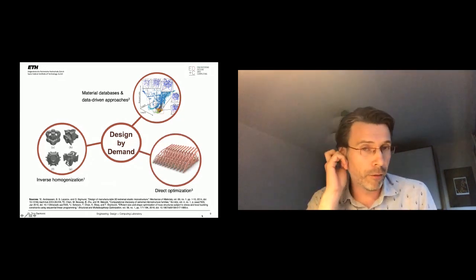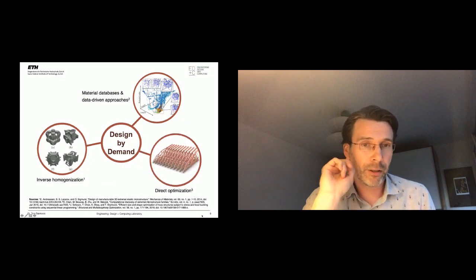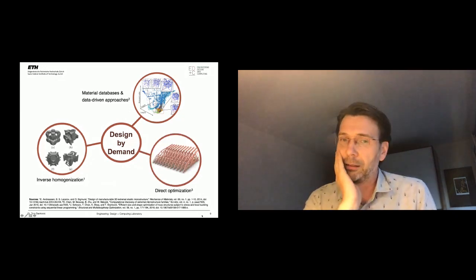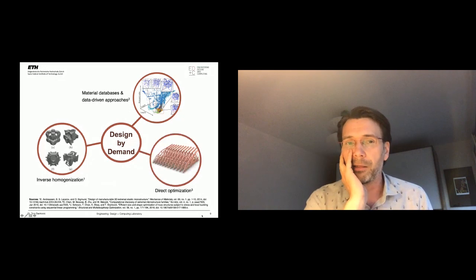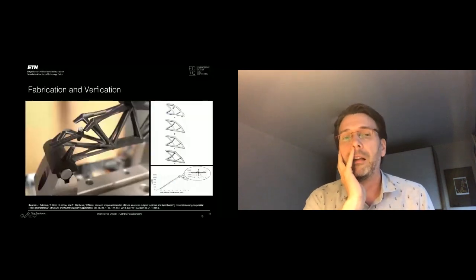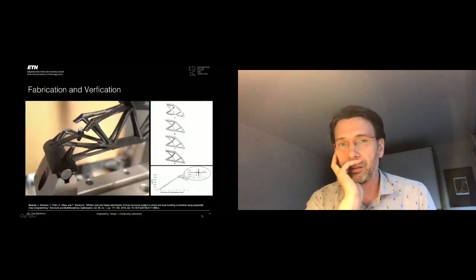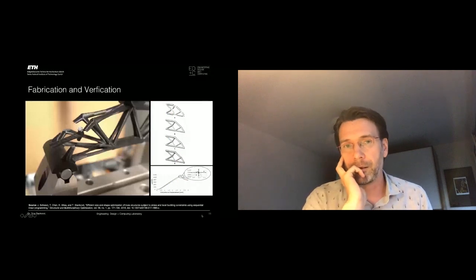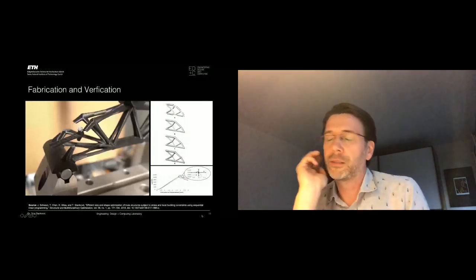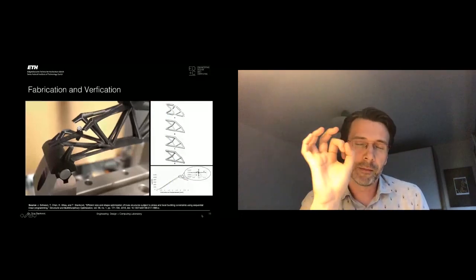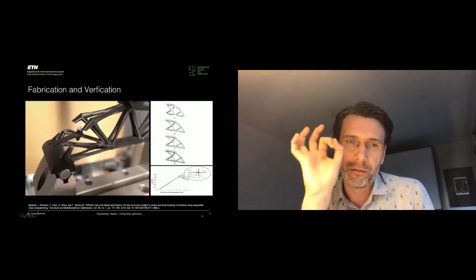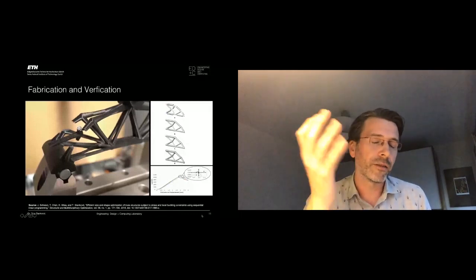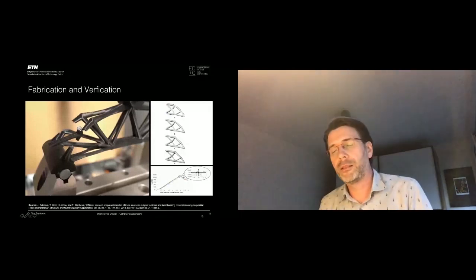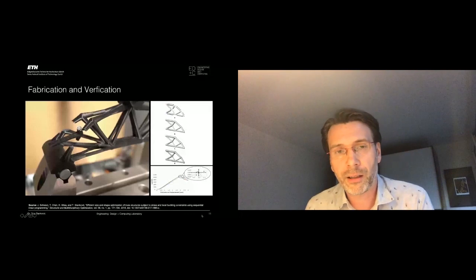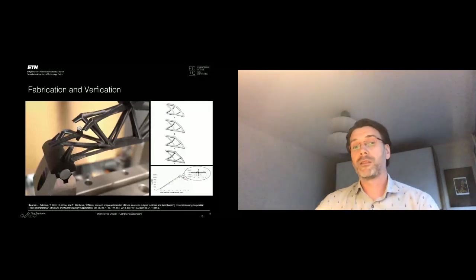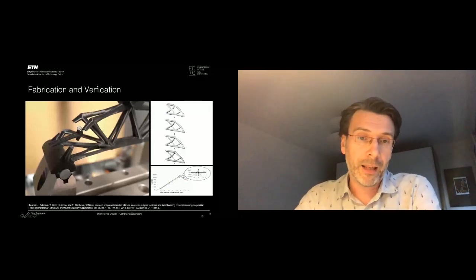So, for example, all of us have encountered this problem. For instance, we optimize this beam here, and then the beam snaps this particular time, somewhere halfway through the bar at the load that we designed for, without increasing the area of the bar around the joints. That happened because we didn't account for the moments in the joints, and of course, then the load was not adequate. But there are also many other reasons that contributed to this happening.